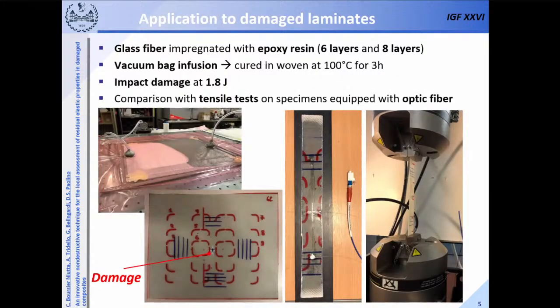To validate the technique, we considered two composites, one made of 6 layers and the other one with 8 layers, made of glass fiber and epoxy resin, that we realized in our laboratories in Politecnico di Torino, and that we damaged by impact. Then we applied the non-destructive technique, and then, to validate it for comparison, we performed tensile tests on specimens that we cut from the plate and that we instrumented with the optic fiber in order to obtain a punctual measure of the strains.